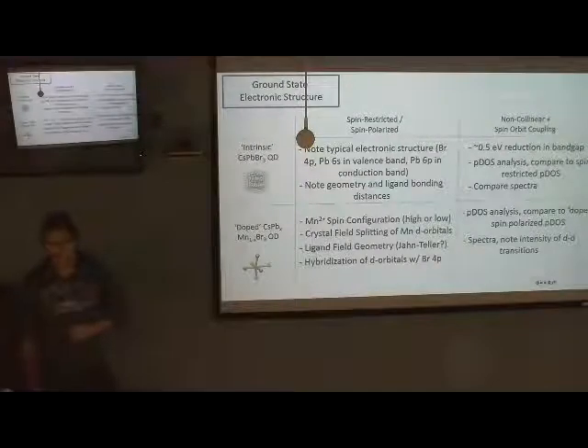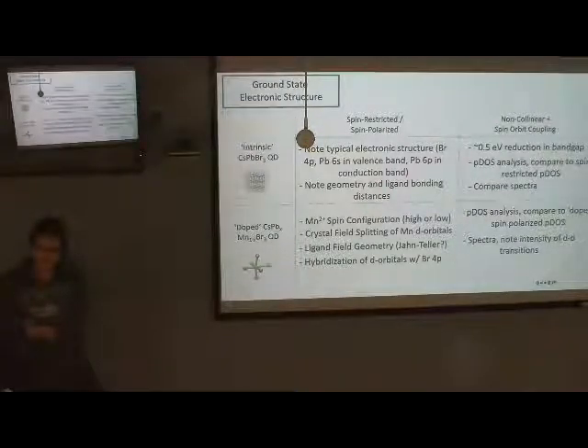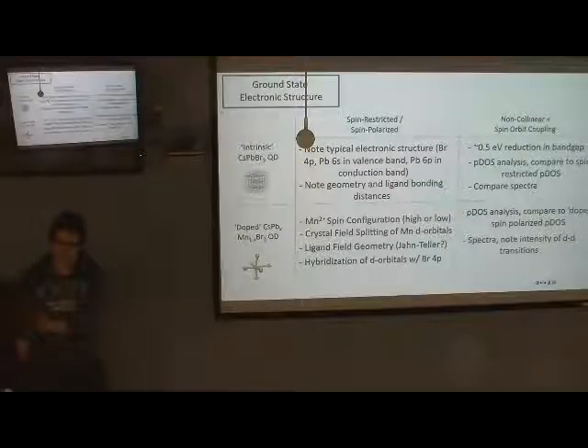Usually it's a very common distortion when you have an octahedral structure, right? And then the bonds on the apical, or whatever you call it, on the top and bottom, from like you have 4 atoms lying on a surface, right? And then the top and bottom ions are either longer than the bonds for your 4 in the surface, or shorter, right? Mm-hmm. So you either squeeze it or elongate it. And then it's also known, from a simple geometrical point of view, molecular orbital theory gives you the splitting between your d levels based on this perturbation. Mm-hmm. But in your case, your perturbation is really just kind of one bond is increased.